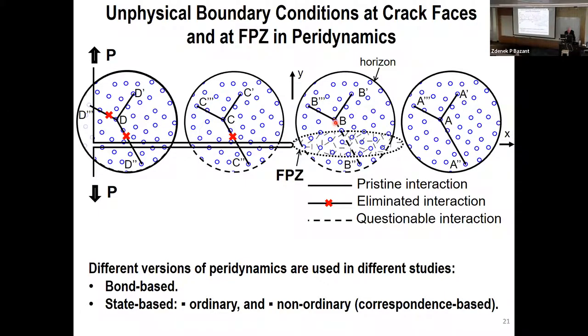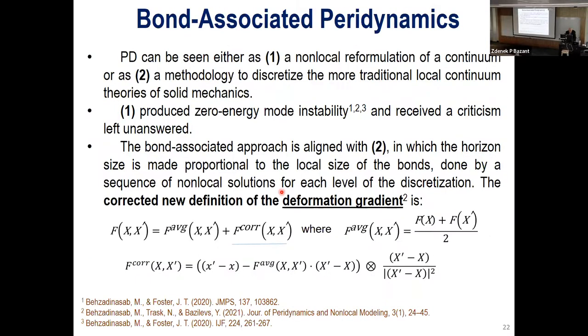So should B interact with B double prime? Well, if it's very close to the front, there's little damage, then it probably should almost fully. If B double prime is located here in the back, then obviously almost not. So there should be a gradual change that has never been considered, but it has a significant effect. So that's one unsolved problem in peridynamics.